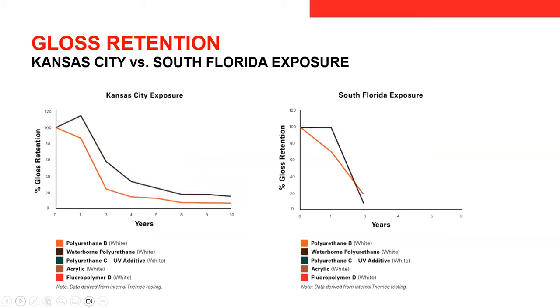Now let's compare two real world exposure conditions in two different locations: Kansas City, a Midwestern exposure, and then South Florida again. In this case, the polyurethane is holding on a little bit better in Kansas City than South Florida, which you would expect. Same thing for a water-based polyurethane and a third aliphatic polyurethane with a UV additive that can help prevent some of that degradation.